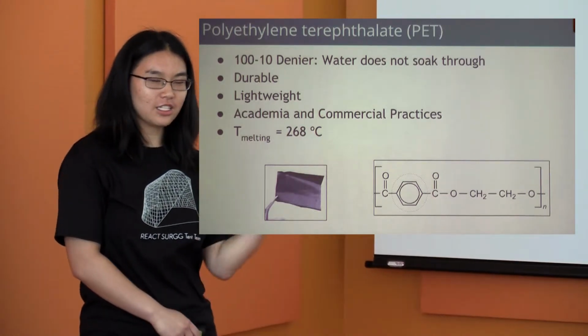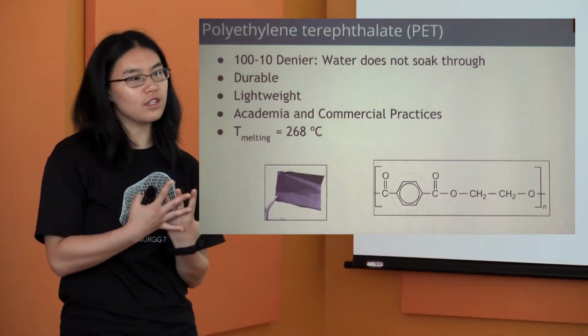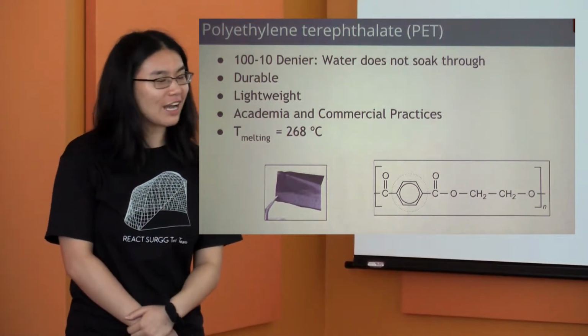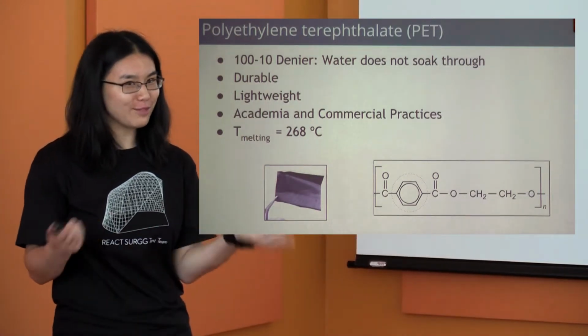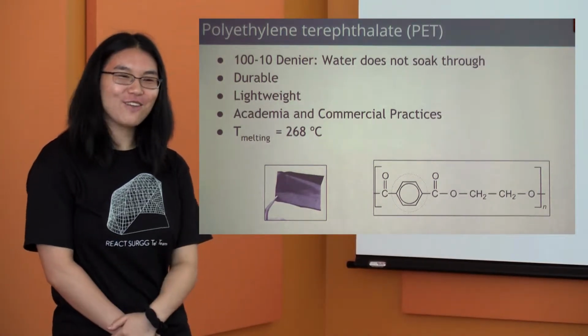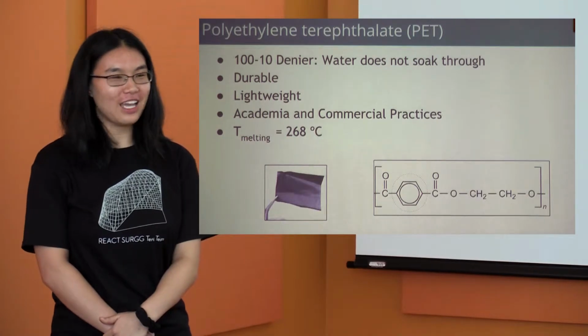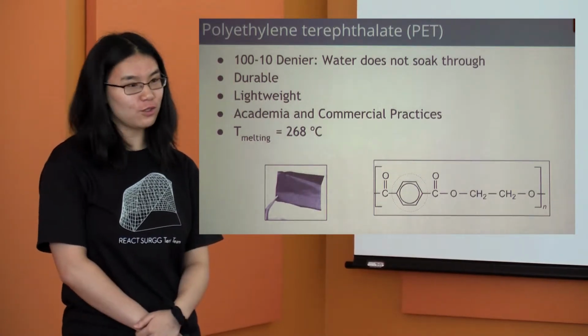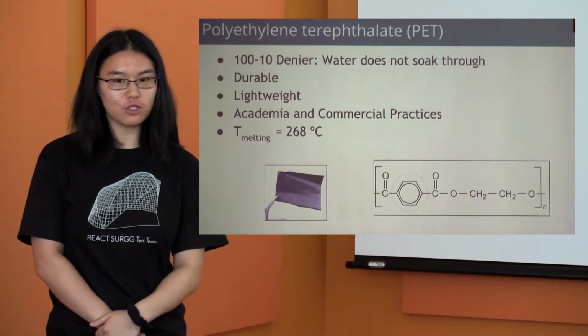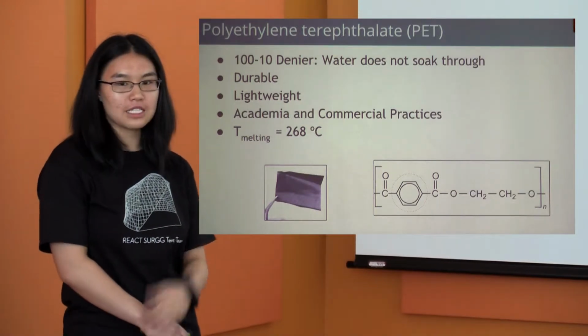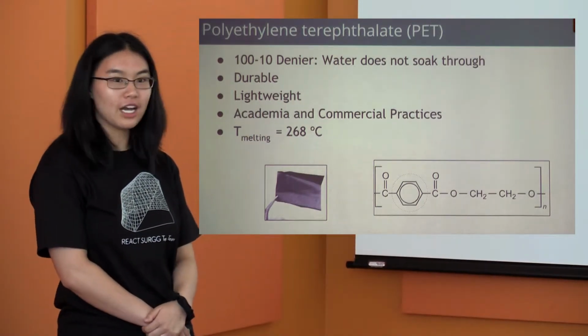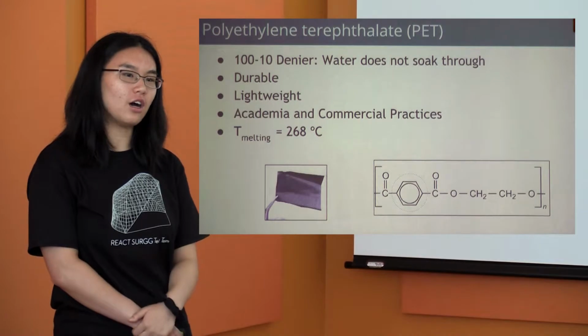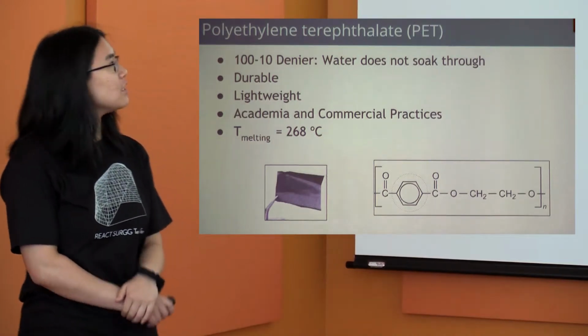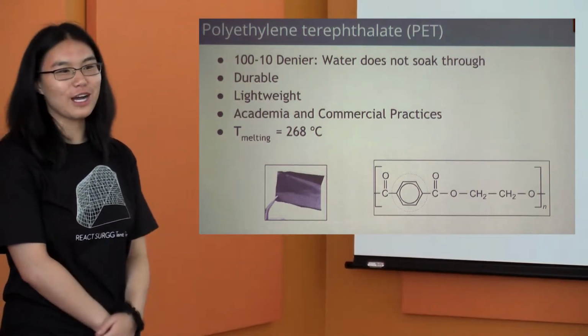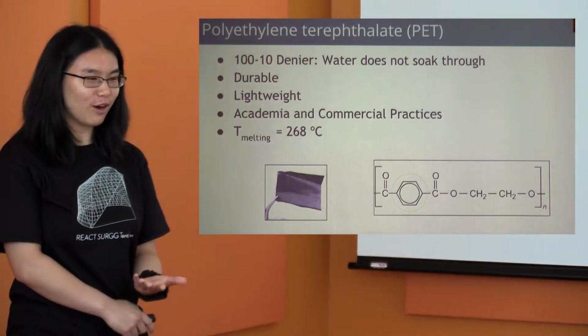This is because at the denier that we chose, which is just how woven the fabric is, the water doesn't actually soak through, which is something you want in a tent, naturally. Furthermore, it's durable, lightweight, and because it's inexpensive, it's also used commonly in academia and commercial practices. Furthermore, its melting point is pretty high, which allows us to use the heat gun on it without any problems. In addition, because of this benzene ring, it's also hydrophobic to begin with,